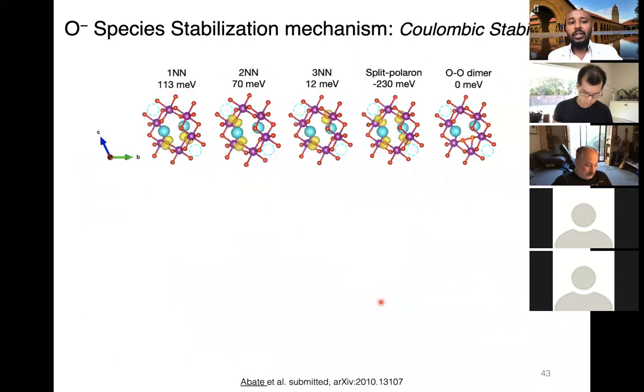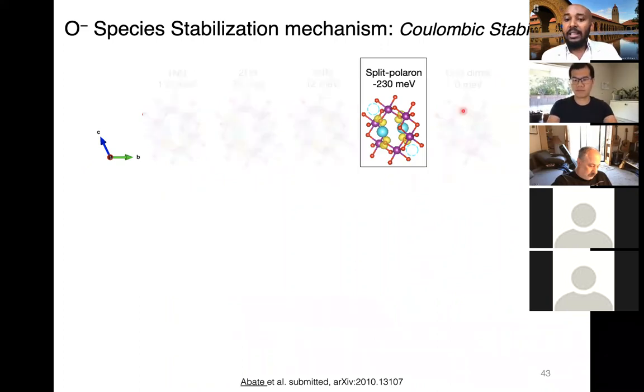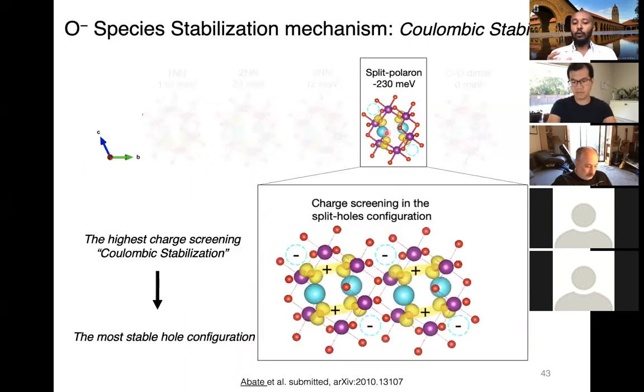So the question then is, why are these O- species only stable in this system, having been discovered previously in a different system that has been explored for the past 10, 12 years? To answer this mechanism of stabilization, we explored different O- configurations or hole configurations in the system, as shown over here, but we found out that the most stable configuration is what we call the split hole configuration, as shown over here. And we found this to be a configuration that maximizes the charge screening, maximizes the Coulombic stabilization between the holes that are formed and the sodium vacant sites that are left behind. Such Coulombic interaction is highly enhanced in such configuration, and that's why the holes are stable.